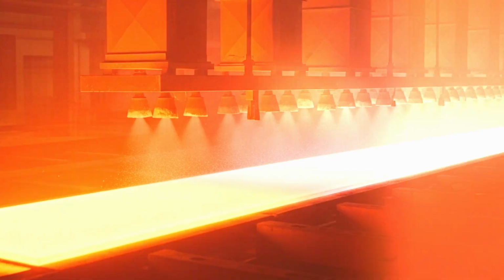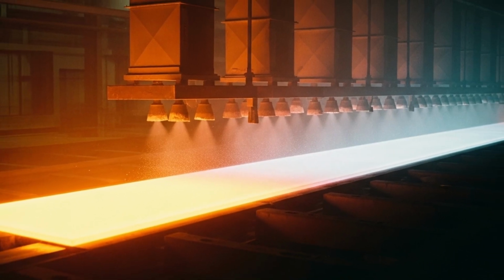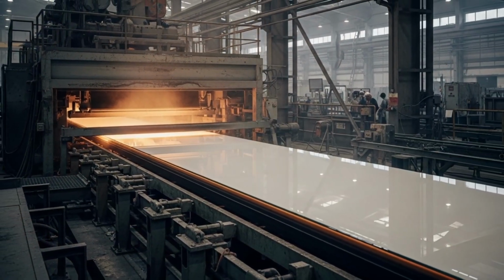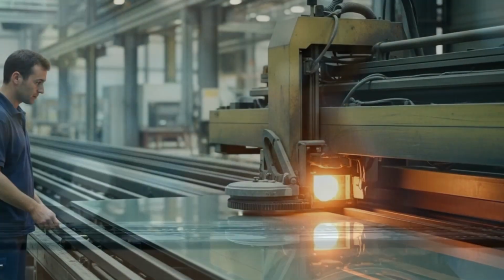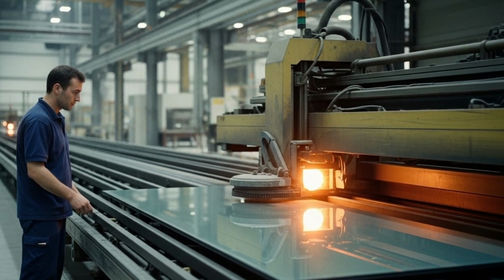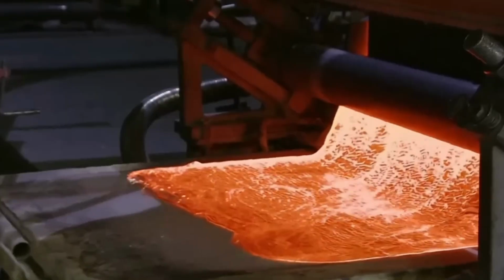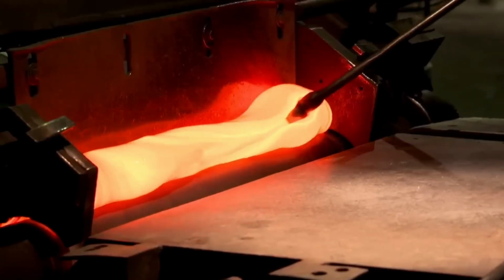As the sheet moves forward slowly, about 1 meter per minute, side rollers guide its width, which can reach up to 3 meters on some lines. It then passes through cooling zones that solidify the glass without warping or waves. At the end of the bath, another 50-meter section, the sheet reaches about 600 degrees Celsius, a temperature high enough to maintain stability before being cut into panels ready for distribution.